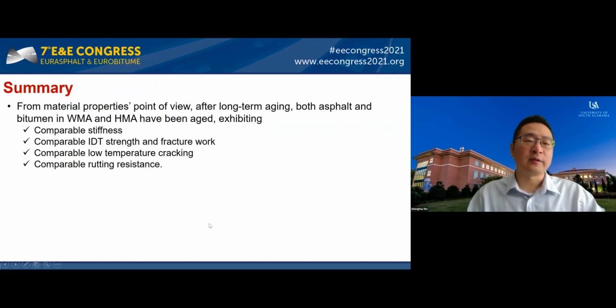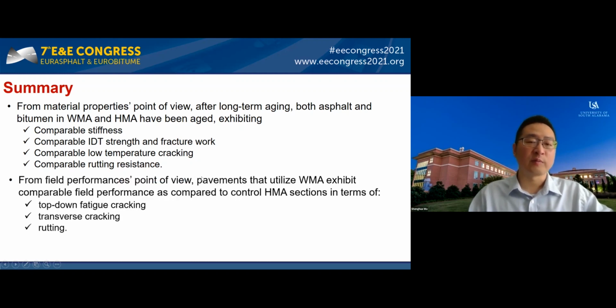So based on our findings, I want to recap what we found for this project. From the material property point of view, after long-term aging, both asphalt and bitumen in WMA and HMA have aged. They are showing very comparable stiffness, IDT strength, and fracture work, low temperature cracking resistance, as well as rutting resistance. From the field performance point of view, pavements using WMA show very comparable field performance compared to the control HMA section in terms of top-down fatigue cracking, transverse cracking, as well as rutting.